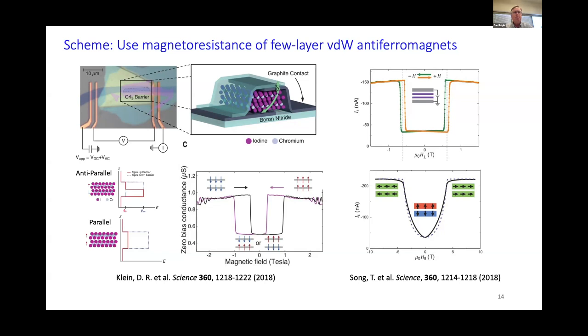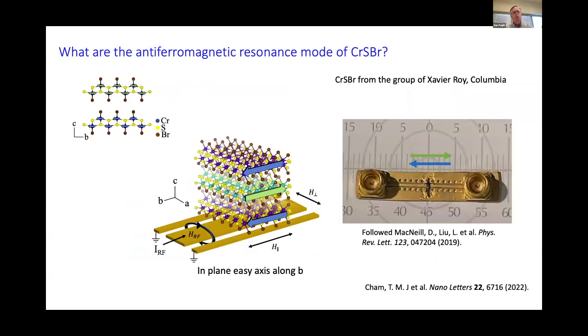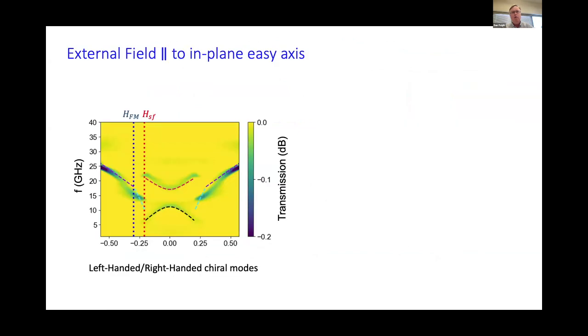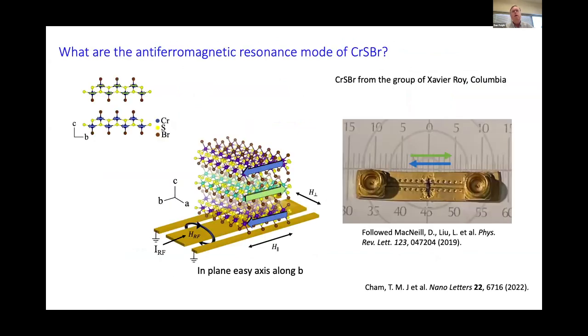Okay. So we've studied the van der Waals antiferromagnet chromium sulfur bromide, which is a nice antiferromagnet, with lots of interest for lots of reasons. For us, it's interesting because it has reasonably strong triaxial anisotropy, which allows us to control the directions of the spin sublattices in nice ways with external magnetic fields.